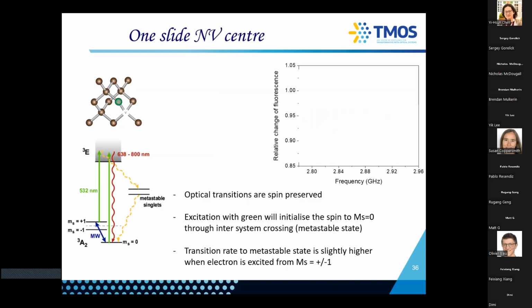So let me give you one slide about NV centers. The reason why NV centers are so cool and hot is because you have this level structure, which creates a splitting in the ground state, and it has a C3V symmetry. And this splitting in the ground state is accessible by microwave radiation, so 2.8 gigahertz. Normal microwave you can buy on eBay for $1,000. And the other thing that this system has is that you can excite it with the green laser, obviously, and the transition rates through the metastable state, which is causing spin mixing, are very different than the relaxation down from the excited to the ground state. So there are two things here.